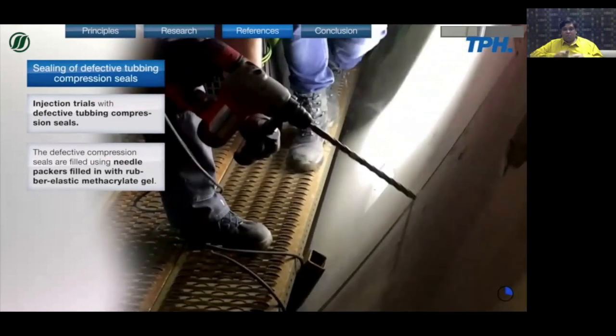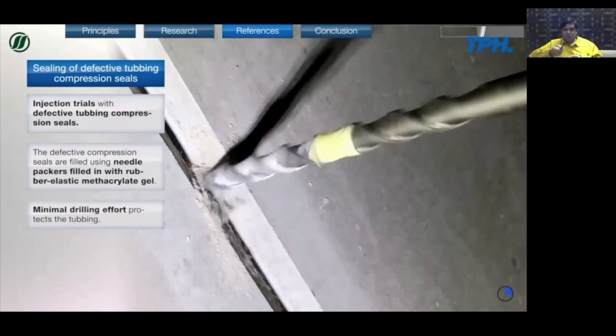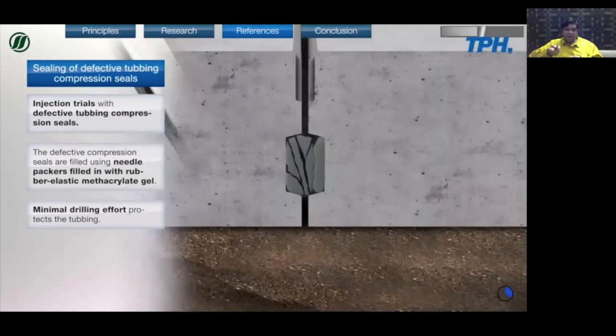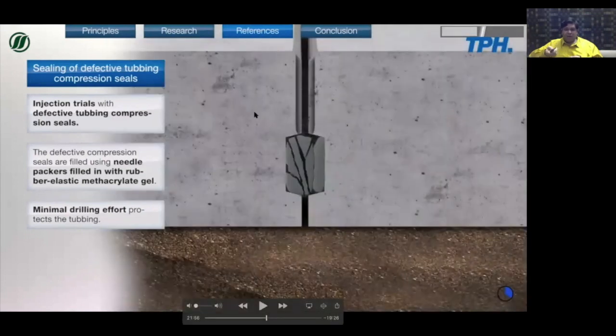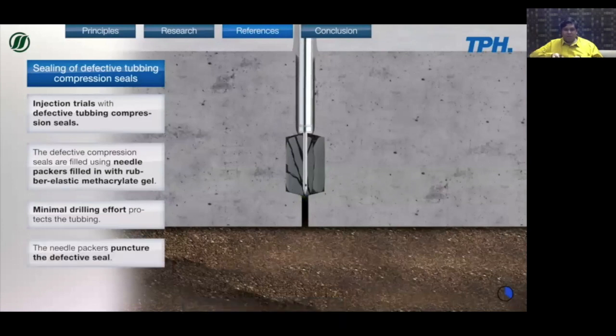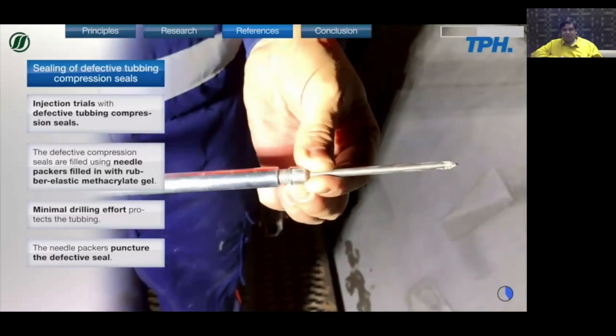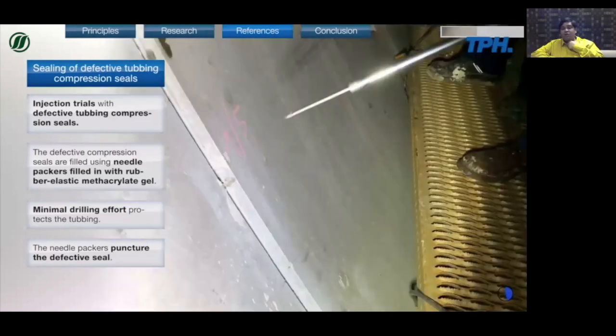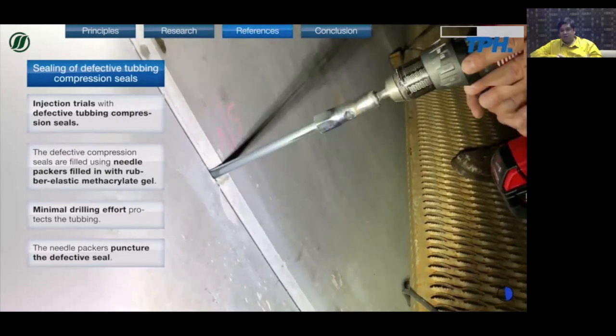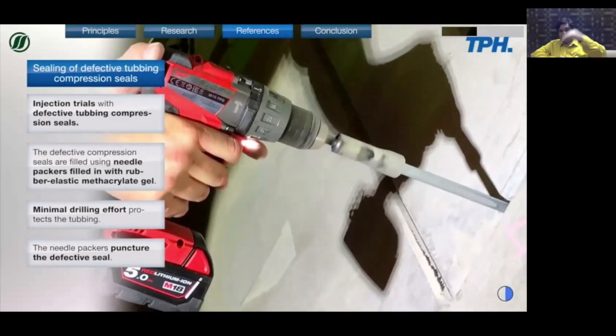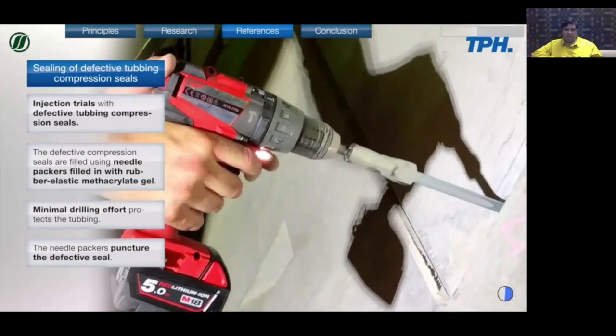So one of the easiest ideas to remedy this is using a needle packer. That means you use a packer and drill right through the defective seal. You use a needle packer to go right through the seal, down to the other side. Let's take a look. You puncture the defective seal, and then you inject the very flexible methacrylate gel so that it forms a curtain on the outside of the tunnel line.